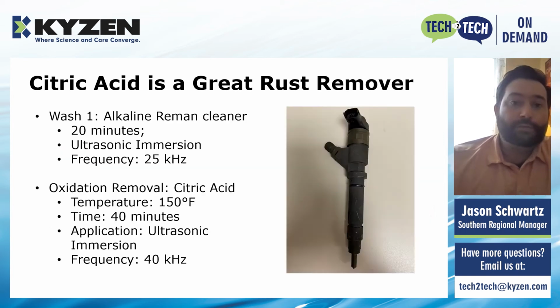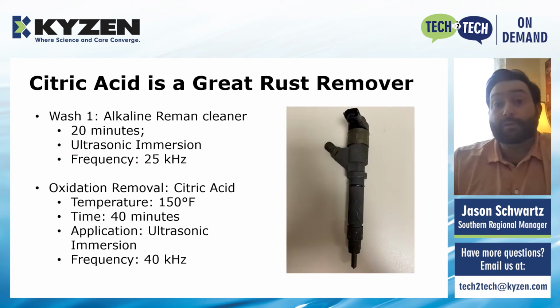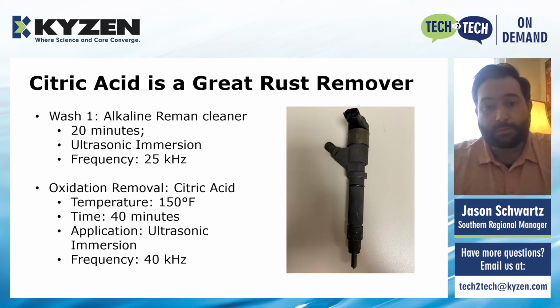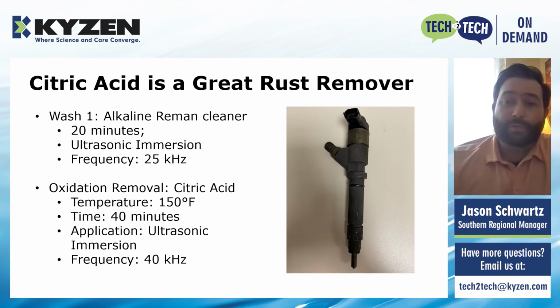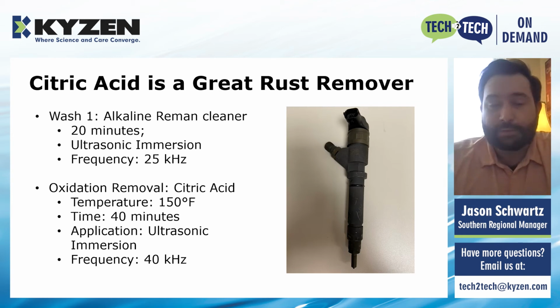So instead, if you do a first step of an alkaline reman cleaner to get all that oil and grease off, especially with some ultrasonic immersion, and then you go into a higher temperature citric acid bath, you're actually going to remove all of that rust. Now, you're still not going to be super happy because the part's going to come out looking like the picture on the right and it's completely coated in black.